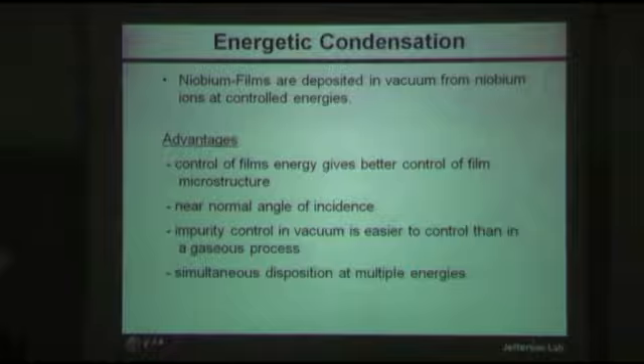Shadowing is also reduced because low energy ions follow electric field lines to the surface and arrive at near normal angle of incidence. And the chamber impurities are easier to control in vacuum than in highly purified gases. I won't go into that, but it's generally true.